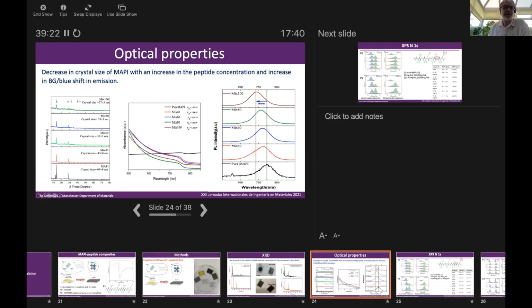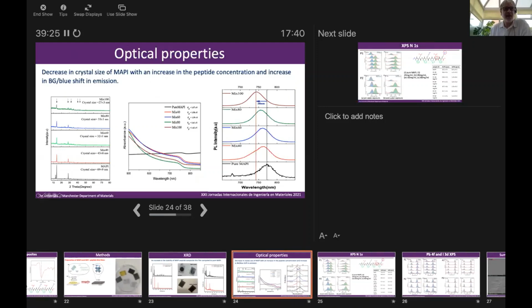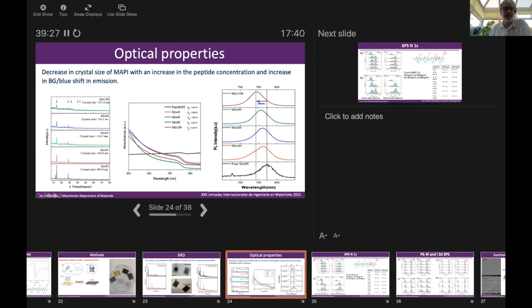Okay. So we wanted to look at the optical properties. So we've got here a range of methylammonium lead iodide perovskite mixes. The number here, 40, means this is 40 milligrams of peptide gel mixed with 1 milligram of perovskite precursor. So we have increasing peptide concentrations as we go up on here.